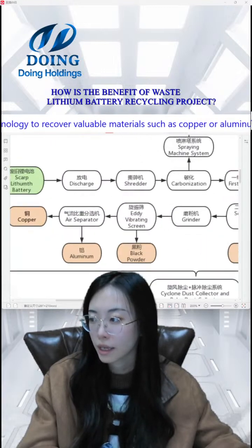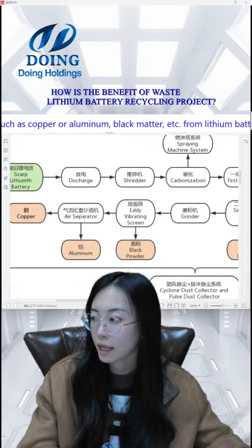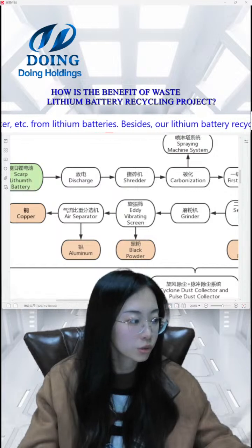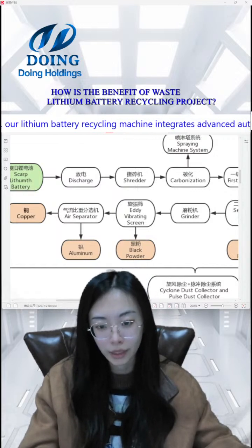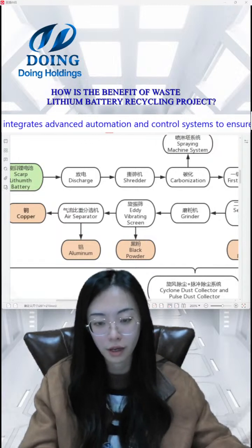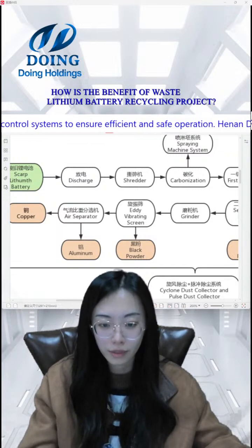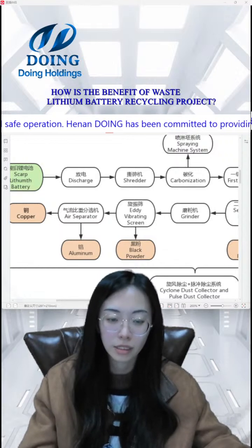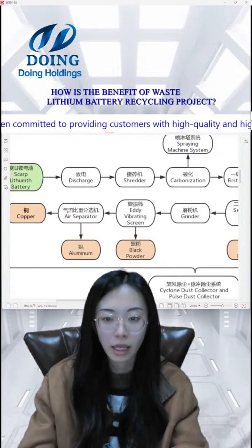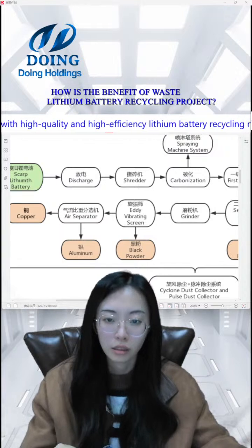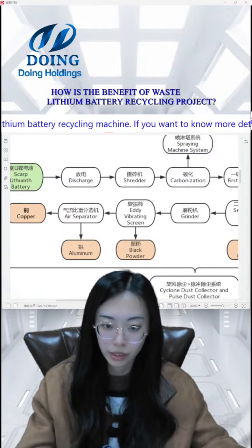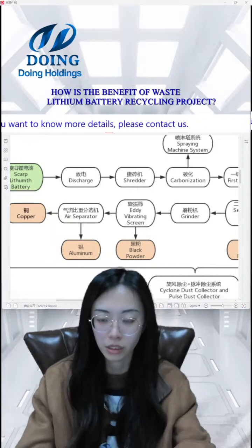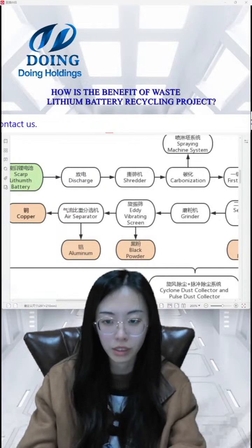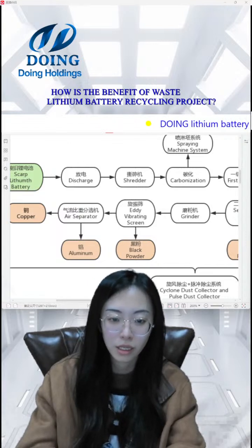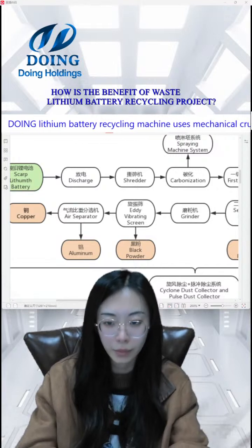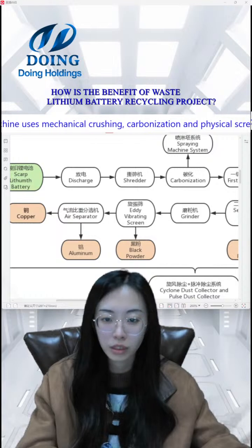We use the air separator to separate the copper and aluminium. But because they are two metals, we can't use the electrostatic separator. We can only use the air separator, but it also has a good effect. This is also called the gravity separator. The air gravity separator utilizes the combined action of the airflow and the vibrating friction on the materials. The larger copper particles will settle to the bottom, and the smaller particles, the aluminium, will be in the front of these materials, to separate them. In this step, the recovery rate of the copper and the aluminium is 98%. This is the whole process of the separating.